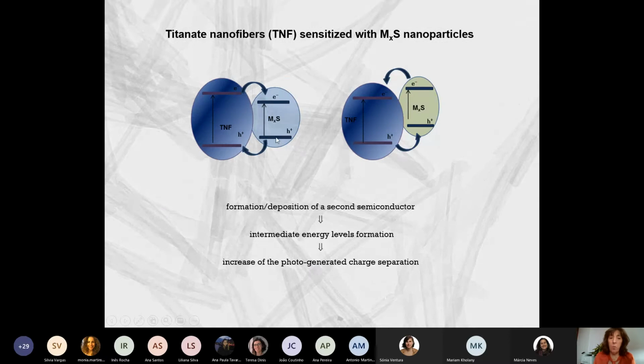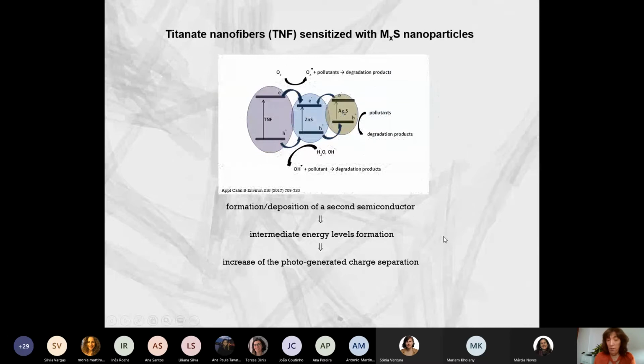So we are interested in combinations that allow us to introduce extra energetic levels, of course, in order to make the use of materials as photocatalysts more efficient. Of course, these are only some schemes, and it depends on us. And here is an example where we have combined zinc sulfide nanoparticles with silver sulfide nanoparticles. This is a kind of core-shell system, and in fact, the photocatalytic performance of this nanocomposite is very promising due to the combination of these three components.